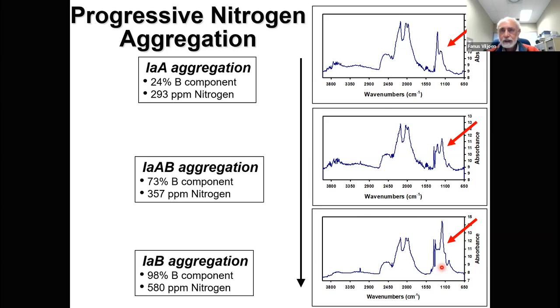Now, again, this is potentially a useful tool. We do find that some kimberlites contain diamonds which are predominantly of this aggregation state. And we do recognize some kimberlites where the diamond population tends to be more dominated by this aggregation state. And that, in combination with nitrogen contents, which can be highly variable between different diamond sources, gives you a tool to essentially make a call with regards to the source of diamonds from different kimberlites which have been amalgamated into an alluvial source.